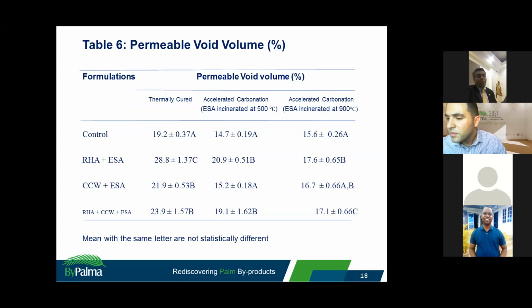Then the void volume, how permeable is the material? From the experiment, it shows the permeability of the material, and even at 900 degrees Celsius, the percentage of increase from that of the control is still minute, because the difference in the values is not so significant. And if you see from the ABC, it shows the level of significance of those materials.